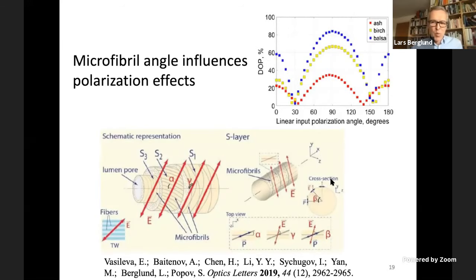And what she discovered was that this is very different for different types of materials. So if you look at the upper right corner here, you see ash, birch, balsa. So they have qualitatively related behaviors, but there's a large difference between the different wood species. And it turns out that the reason is that they have very different microfibril angles. And this property turned out to be very sensitive to polarization effects.